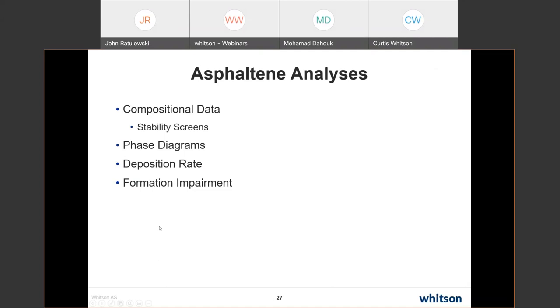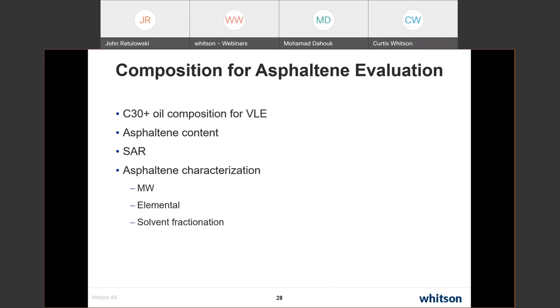All right, so composition, which is really important for evaluation of potential asphaltene problem, C30 plus for the VLE. Asphaltene content is key. You're gonna have to measure an asphaltene content. Usually we'll use heptane precipitation in order to measure that content. You can also use pentane, but it is important to look at how this is measured because it's not always the same technique.